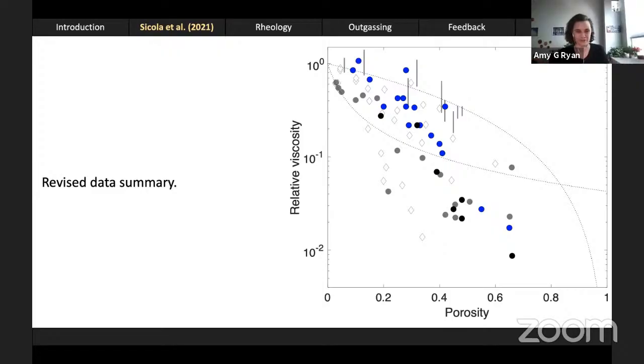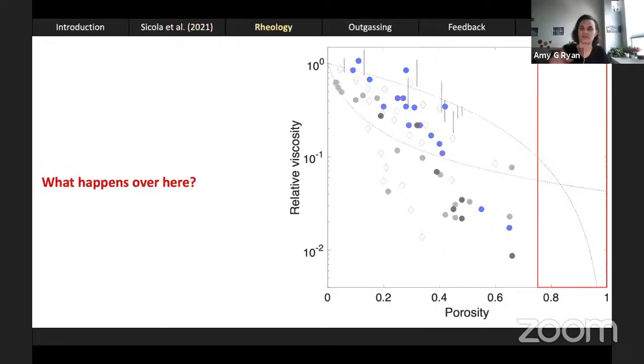Coming back to my final slide. So while Stefania was working on all of this, I wanted to know what happens over here in this red region where there's no data. And it's worth noting that above porosities of about 0.74, 0.75, which is delineated by this box, the material is better described as a foam than a suspension, which is more applicable to porosities below 0.74. Nonetheless, magmatic foams happen in nature, so it's worth knowing what's happening over here in this region.